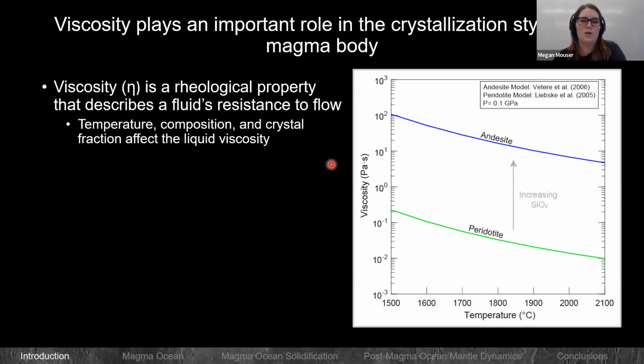You're going to hear me talk a lot about viscosity today because it is a really important parameter when thinking about magma bodies. In basic terms, it's a rheological property that describes the fluid's resistance to flow. And this property is sensitive to temperature, composition, and crystal fraction. If we take a look at what I have plotted over here, I have plotted the viscosity of a peridotite liquid and an andesite at 0.1 GPa over a range of temperatures. If we just look at the temperature component for both, at the lowest temperatures they have the highest viscosities, and as you increase in temperature, each respective liquid reaches its lowest viscosity. So there's the temperature sensitivity there.